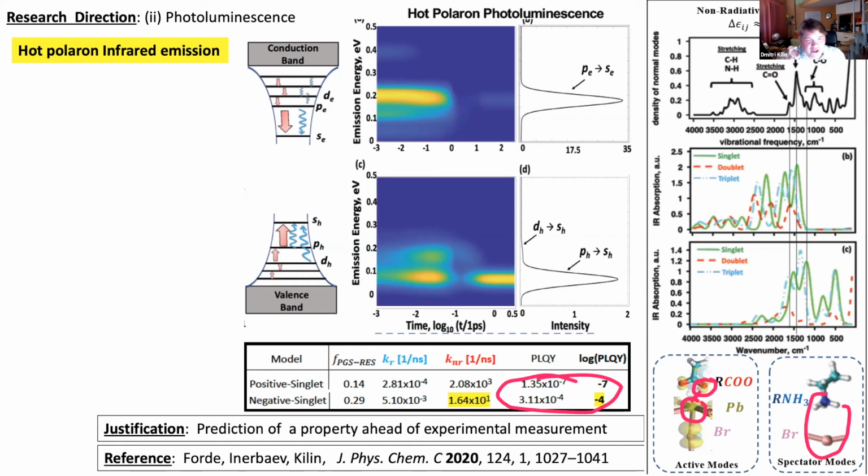So the lowest transition becomes of quite low energy, in the infrared region. And then we just apply the same machinery as before, and non-adiabatic couplings naturally exhibit more intense values if the transition energy is in resonance with some oscillation.